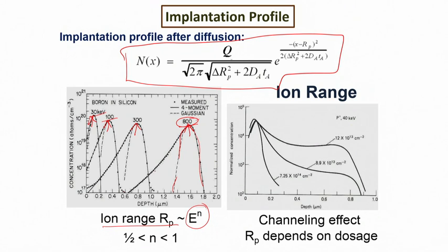There will be a reasonable gap between the two, and this is purely because the ideal is geometrically considered, whereas in reality there will be a distribution of acceleration energies that the species carry, and as a result there will be a long tail below the surface.